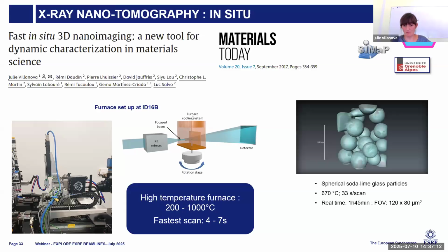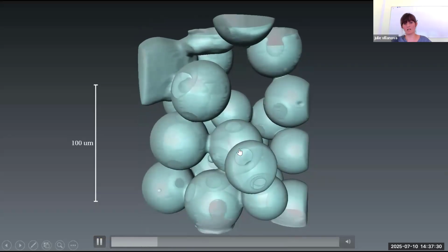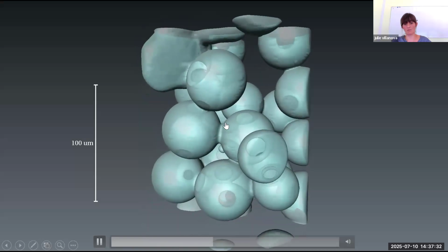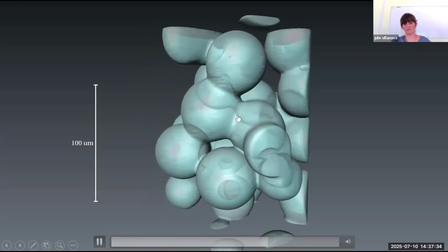So the very first experiment that we performed was sintering of glass particles. Basically, we put some glass particles in a quartz capillary, and we put the quartz capillary in the furnace. We heat up at 670 degrees, and then we were performing scans of 33 seconds for almost 2 hours. And then you can see the sintering, and we were looking with high resolution at the evolution of the neck